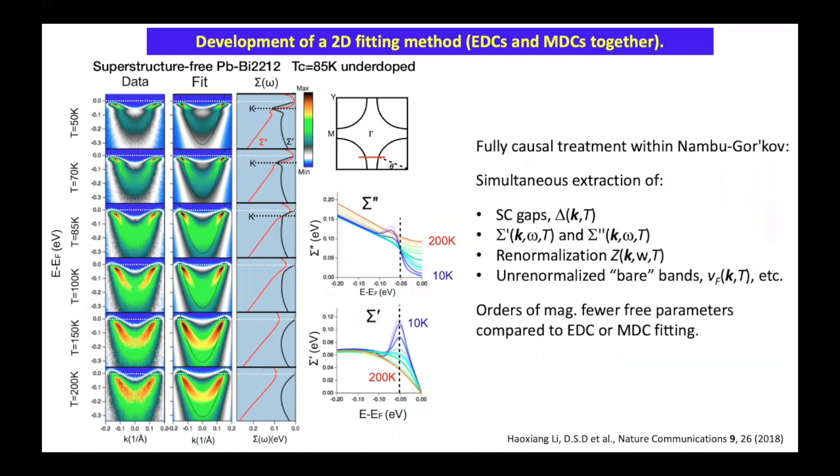Okay, but at low temperatures in the region and low frequencies, I have a drastic dropping of sigma double prime. Along with that, I have a peaking in sigma prime, and this happens because of causality, because of Kramers-Kronig. And these are constraints that go together. Okay, so maybe this is one of the main messages. As I go through Tc, I have a huge drop in sigma double prime. Of course, there's a gapping of the spectral weight as well. These are the sigma prime and sigma double prime as a function of temperature and frequency that make each of these fits that are all working extremely well.